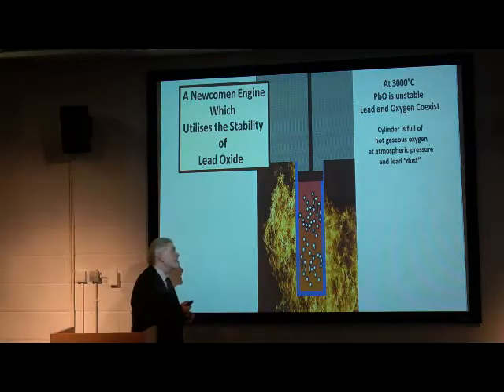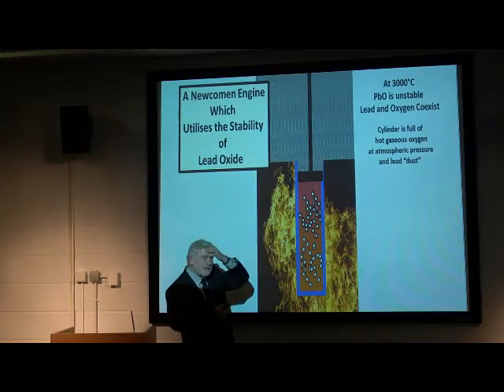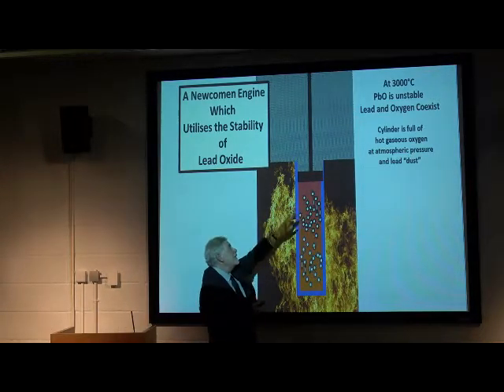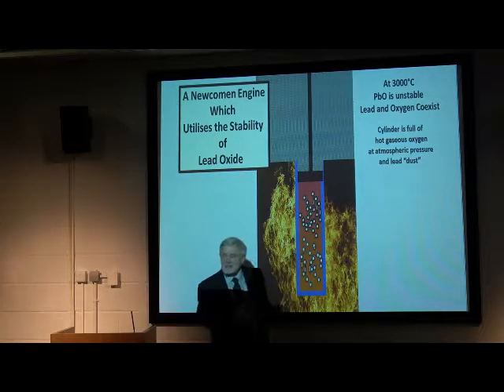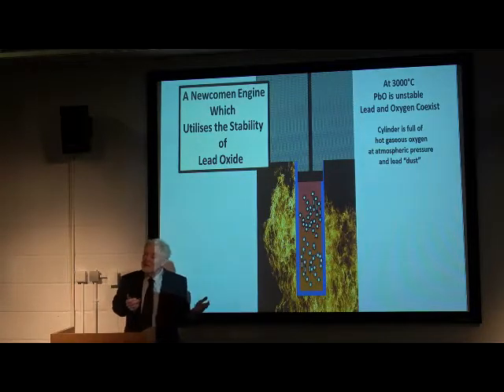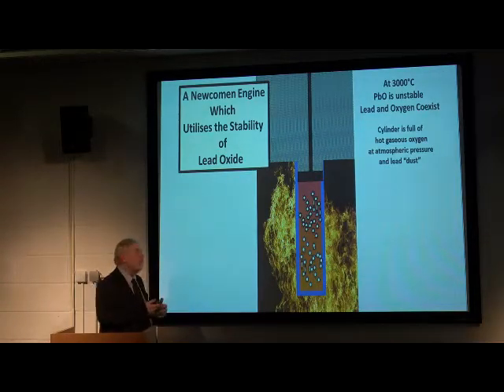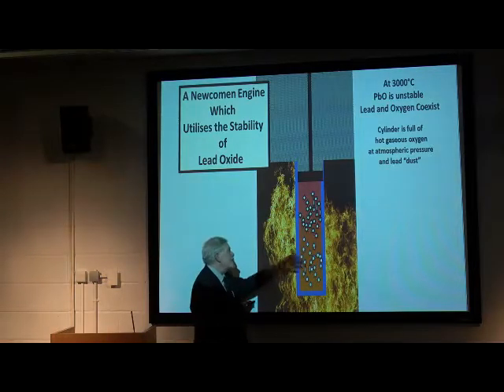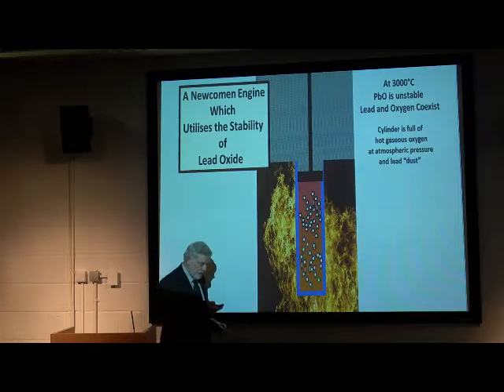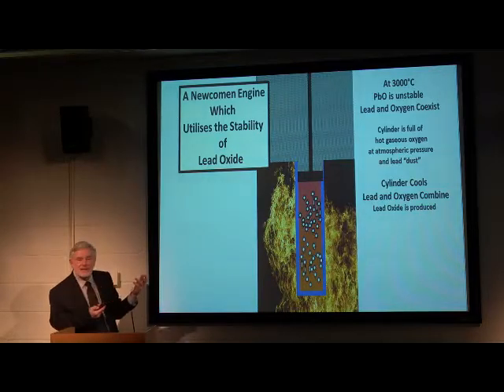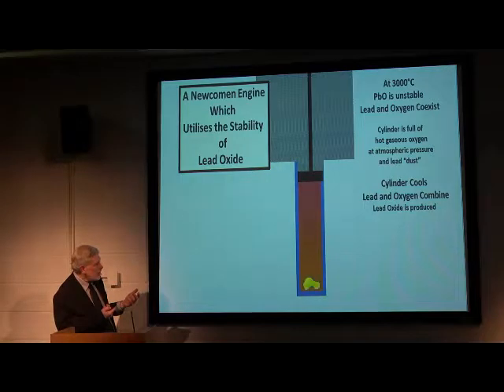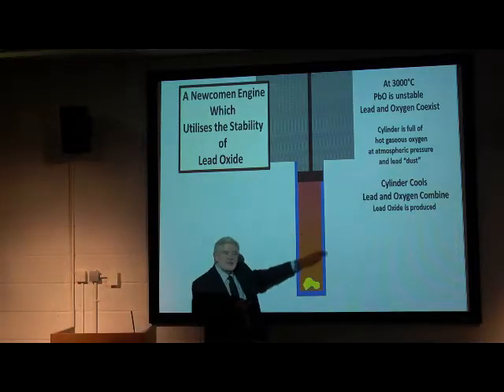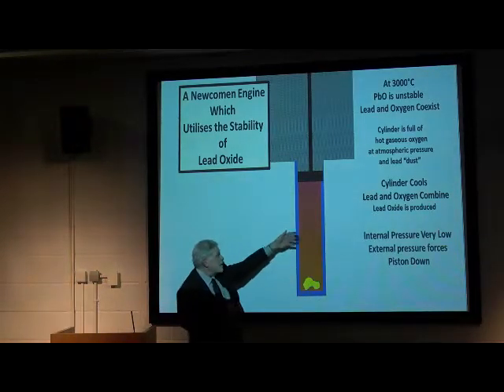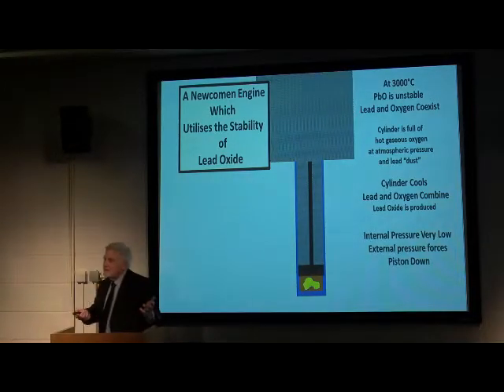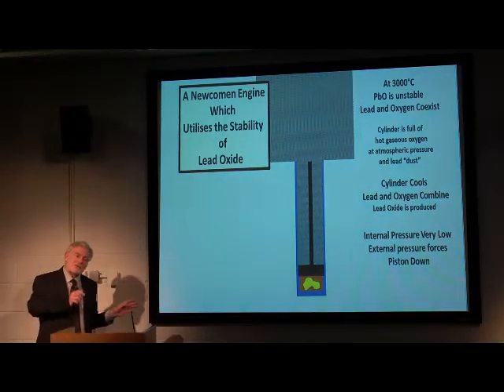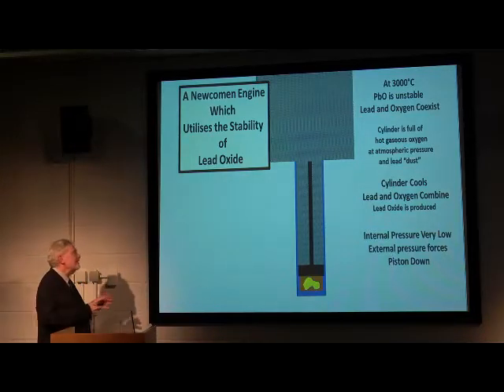I tried to keep this realistic. Supposing we had a wonderful cylinder that could withstand 3,000 degrees, and we could heat that up, and we put lead and oxygen inside of that cylinder. Well, again, as I was talking about in terms of water, if you get the temperature high enough, everything will decompose. So what we're showing here is a mixture of lead particles and oxygen. Now, I cool down the cylinder, the lead and the oxygen combine. Lead oxide is produced. It's used up all the oxygen in the cylinder, and so the pressure is now very low, and the piston comes down. Exactly the same as with the Newcomen engine. So you can now go away and write papers on the thermodynamics of the Newcomen engine.